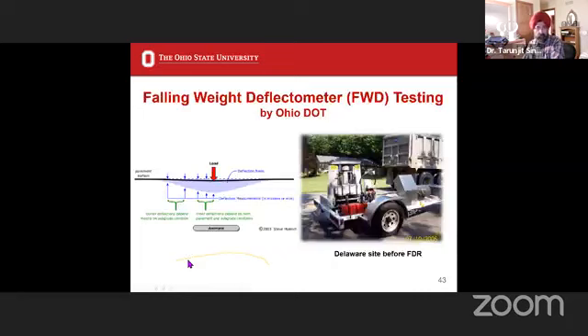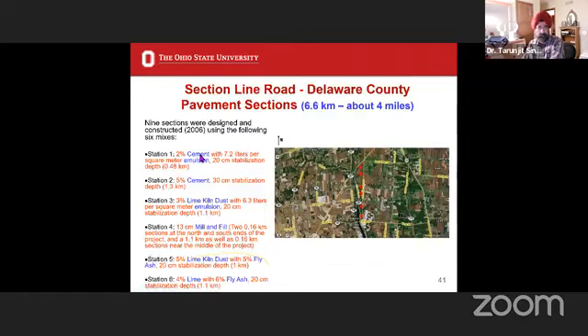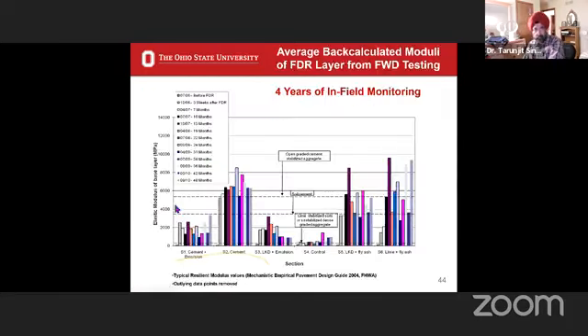If I go back and look at S1, 2% cement with emulsion, this at 5% cement. Or we should have added more cement. So these are the learnings that we get as we go through. If you were to go back and reconstruct this, I would increase the cement. I would actually do some more lab testing first, with more cement, and cement and emulsion, and see if I can reduce the cement but increase the emulsion. This did not work for us.